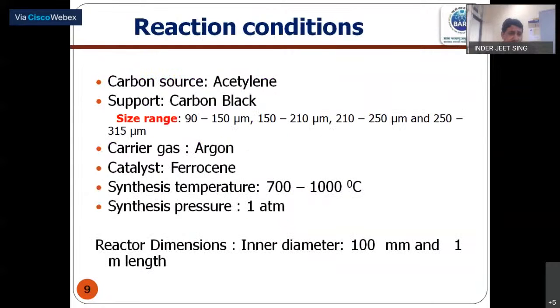Now in our method, we have used carbon source as acetylene, which is readily available and cheap, as a support material carbon black. I will explain in the next slide why carbon black. It has beautiful properties and is a very cheap material. Then carrier gas as argon, catalyst as ferrocene. Ferrocene is an organometallic which you can vaporize easily, and then on cracking it gives iron nanoparticles. The synthesis temperature is in the range of 700 to 1000 degrees centigrade, and I have also given the dimensions of the reactor here.